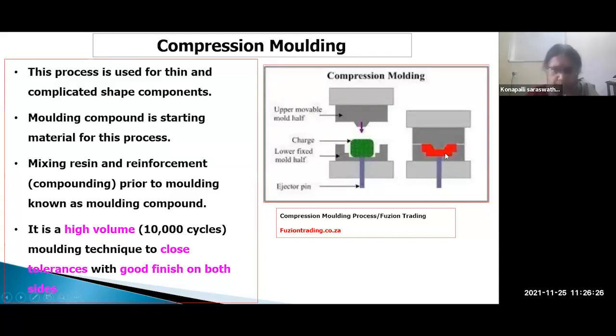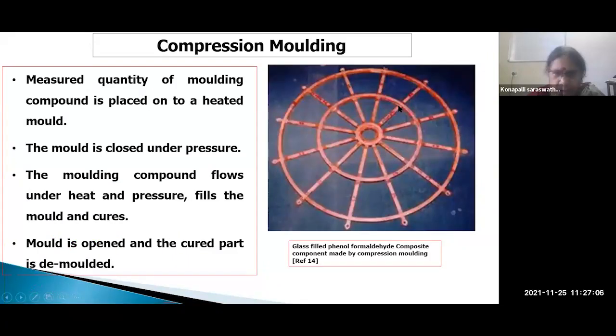In compression molding, very high pressure is applied. That is why it's called compression molding. Compression molding is used when a very high volume of products has to be made, with close tolerances and, of course, surface finish, because on both sides we get surface finish here. One side, die side. A quantity of molding compound is placed in the mold. The mold is closed under pressure. The molding compound will flow under the heat and pressure, fill the mold and cure. This is the molded component, complicated shape. Very thin and complicated shape components are made by the compression molding technique.